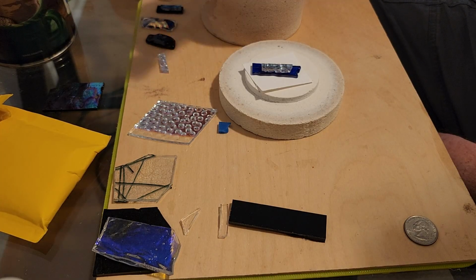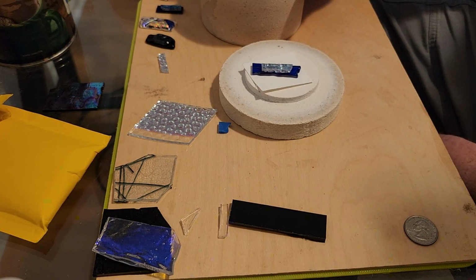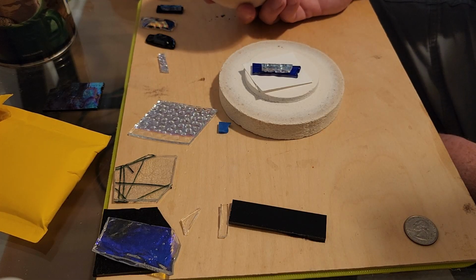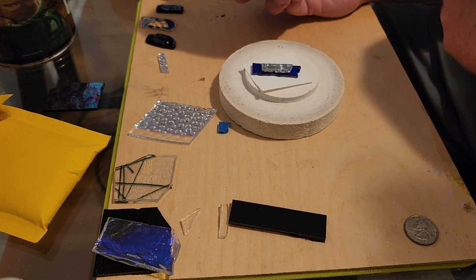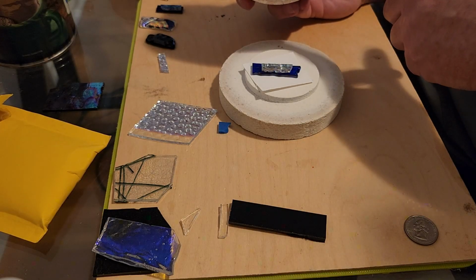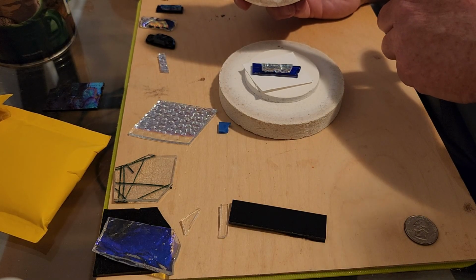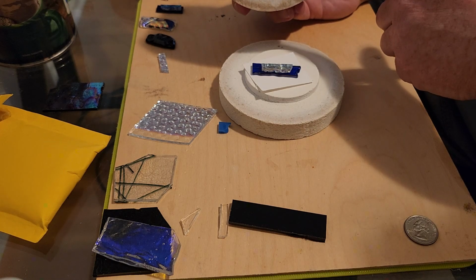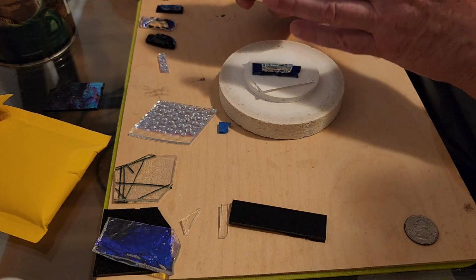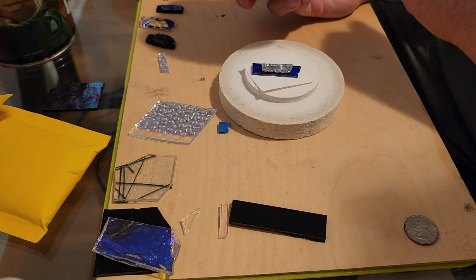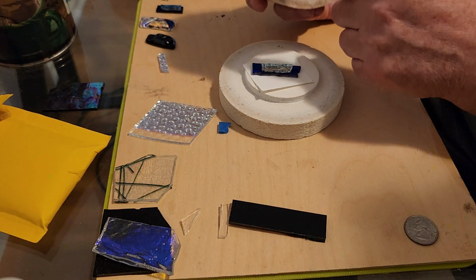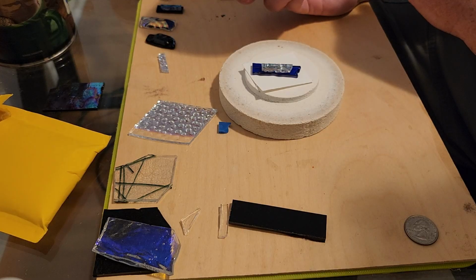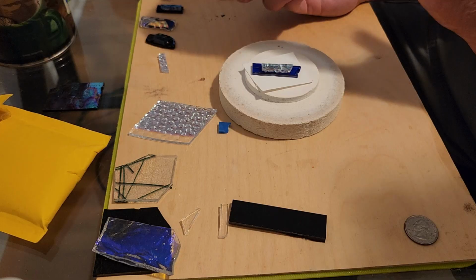The other thing that can happen is it'll just literally destroy your kiln. They'll crumble. Research I've done, the stuff inside the kiln that actually gets hot is called silicon carbide, basically what's on sandpaper. And they glue it in there with something called water glass. Not sure if that's exactly how this is made, but it's a general idea. And it can only take so much heat at once. And you can tell just from looking at it, it gets quite hot. You want to keep that just to a warm orange glow and not go anything past that.